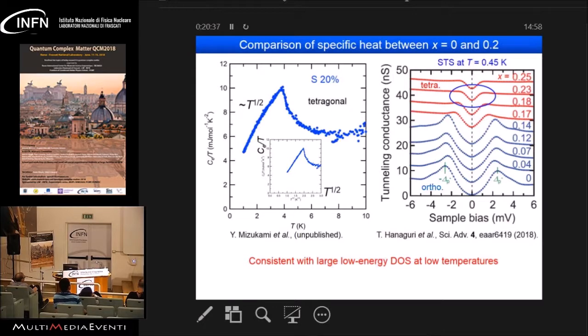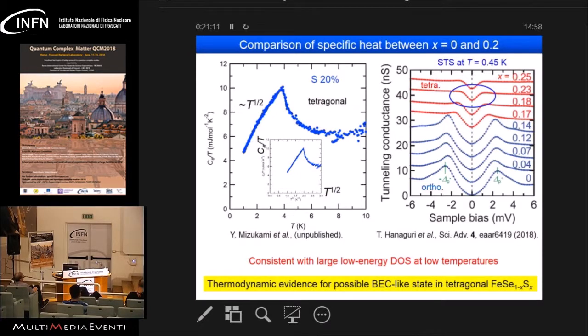And it's not clear from the figure, but we have a finite zero energy density of states in the tetragonal phase. Okay? And this zero energy state is quite consistent with this C over T data, because this data was taken at 0.4 Kelvin, which is around here. So as you can see, we see a quite remarkably large density of states, C over T, even at low temperatures. So these two data give a quite consistent picture. So from this, we conclude that this data shows a thermodynamic evidence for a possible BEC-like state in this material. And I think this is the first thermodynamic evidence for any kind of solids for the BEC-like state in the superconducting system.